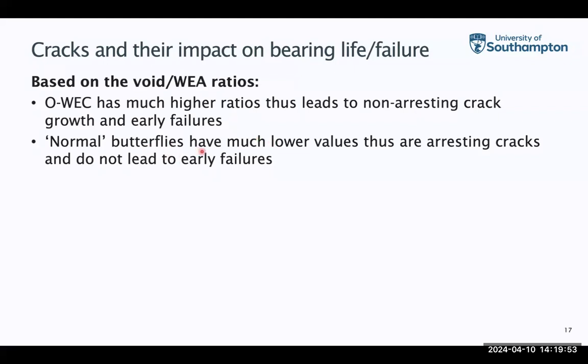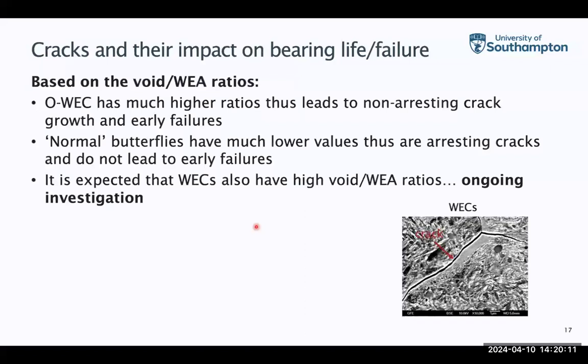With the normal butterflies, and we're not considering very large butterflies, which we know lead to early failures, they have much lower values of the ratios. So that's why they arrest and don't lead to failures. We expect that white-etching cracks would show similar values or a similar phenomenon to the oriented white-etching crack, but unfortunately we haven't done this kind of analysis. It is quite time consuming and very difficult to get all the details. So this is ongoing, and we're expecting to get some conclusions on white-etching cracks, which is the topic of interest to many people.